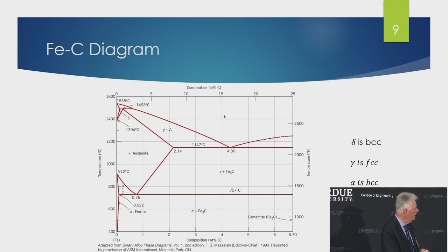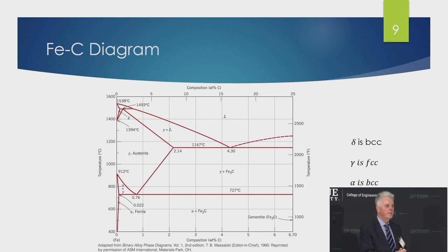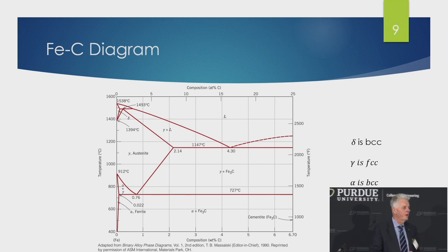So anyway, you can see as carbon increases, all of a sudden you run into this situation where you have a deep eutectic and you get to a very low temperature compared to 1500, where at 1147 you can form a liquid iron-carbon alloy. But what does this mean in practice? This means that as you're reducing the iron with carbon and it picks up carbon, it transforms from solid to liquid and drains. Now all of a sudden you have a liquid draining by gravity from the material you're reducing, and you have effected the separation of the iron from the burden of the other oxide.